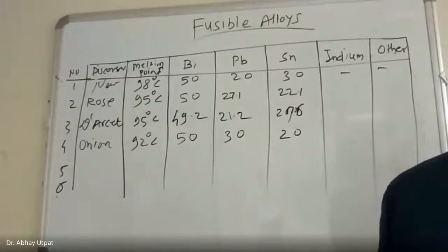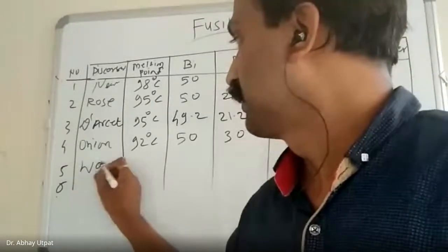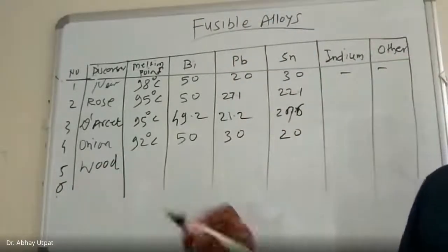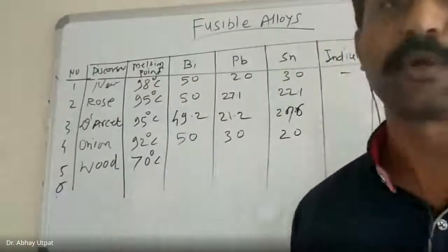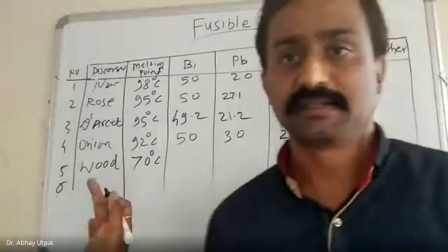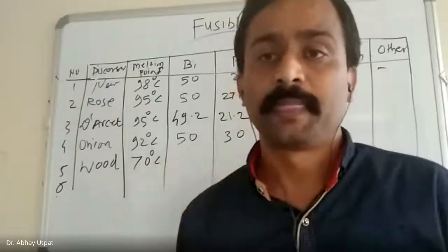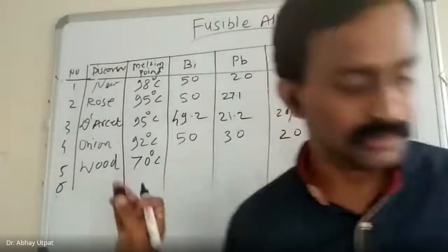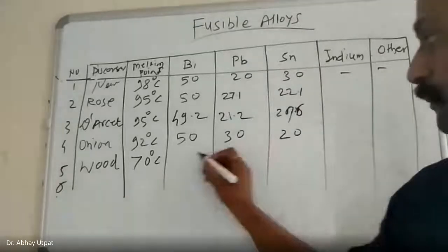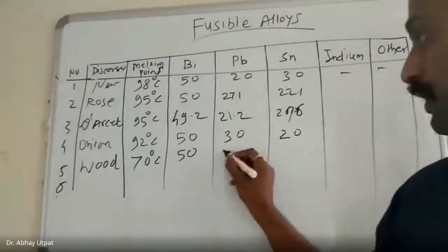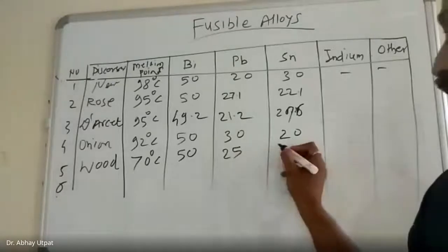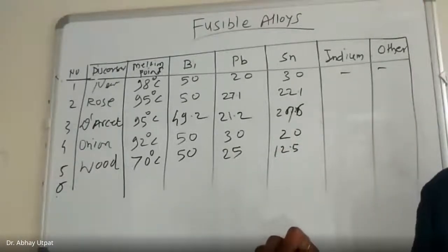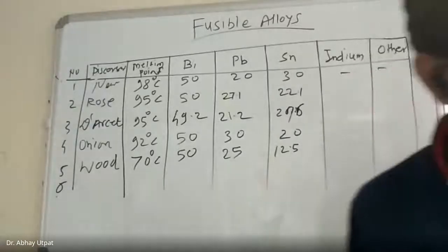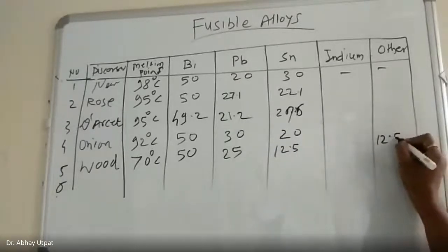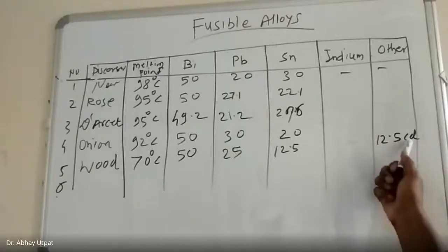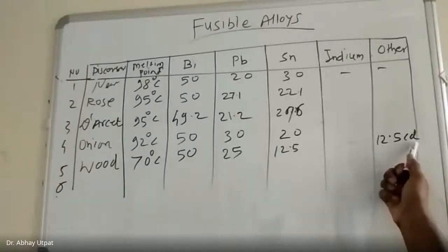Then around 1860, Wood has achieved a much bigger temperature drop, almost 70 degrees Celsius, so far below this 92, 95. So a 25-degree temperature drop is obtained by Wood with the combination 50% bismuth, 25% lead, 12.5% tin, and one more element, 12.5% cadmium. In others you write Cd. Here, friends, I have written 12.5% cadmium in the others.